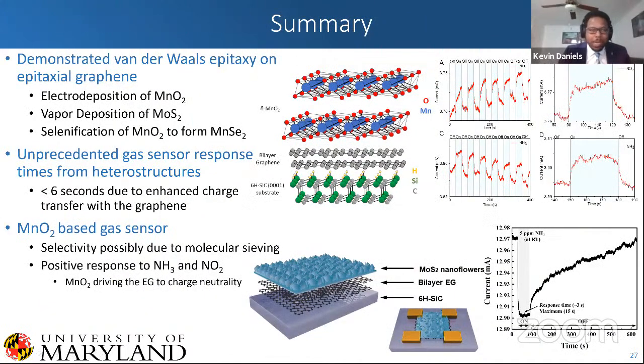So in summary, we've demonstrated this van der Waals epitaxy on epitaxial graphene by electrodeposition and vapor deposition, as well as the latter of the selenization, and we've shown this unprecedented gas response times for the heterostructures of less than 6 seconds, due most probably to the enhanced charge transfer with the graphene, basically charge hitting this superhighway. And from the manganese dioxide gas sensor, we've seen this selectivity, possibly due to molecular sieving, as well as this positive response to NH3 and NO2. And this is possibly due to the materials driving each other to this charge neutrality.